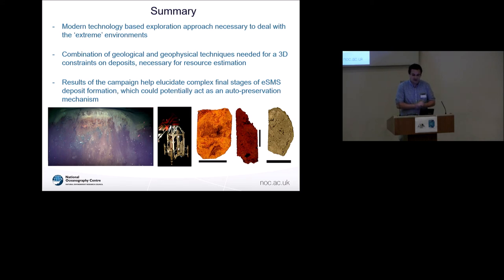And finally, we've got evidence provided from the samples that we've obtained that give us a nice insight into some of these complex formations and these complex processes that are forming at the end of this deposit itself. And we've got potentially evidence for an auto-preservation mechanism, effectively creating this impermeable barrier over these sulfide deposits on the seafloor, which is quite nice if you want to try and mine them in the future, because you've still got the nice ore material preserved.